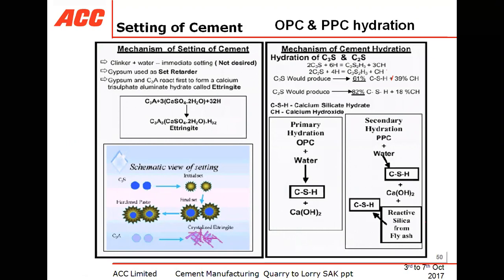So therefore it is said that the PPC is very useful in terms of strength and bonding properties, because you will get secondary reaction. You will get benefit of reactive silica present in the fly ash, which reacts with calcium hydroxide present in the OPC. This calcium hydroxide reacts with your silica present in the fly ash to produce another secondary reaction. Secondary reaction होने के बाद you will get better strength and higher strength to the PPC cement. Therefore, it is said that PPC is more durable than OPC. PPC and PSC both have good durability and good later strength than OPC, because this reaction continues for a longer period.